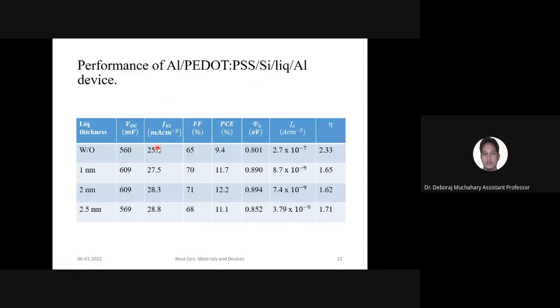Okay, so speaking of the performance of this type of device, the efficiency is around 9.4, 11%, 12%, and 11%. So with the help of the thickness of this layer, what they have done is vary the LiQ layer thickness. They have varied 1 nanometer, 2 nanometer, 2.5 nanometer, and show the different parameters. And these are the junction parameters, because this is a Schottky barrier, Schottky junction. So of course there will be Schottky barrier, there will be saturation current, there is ideality factor. So these are the values they have found.